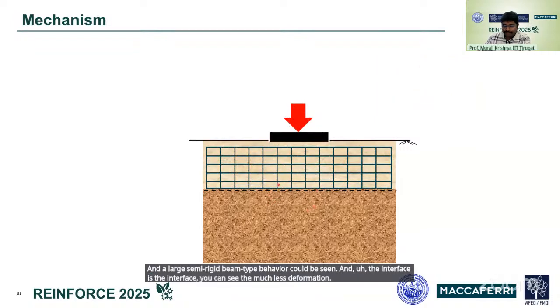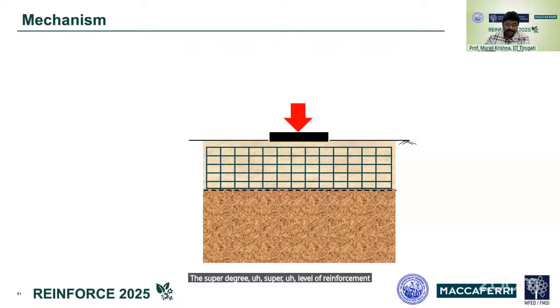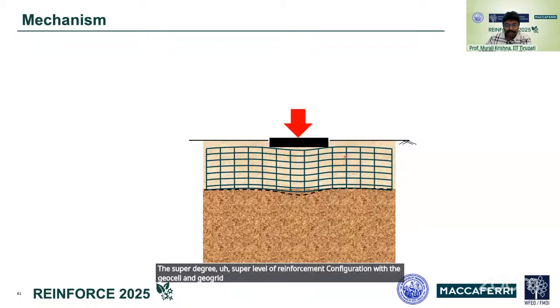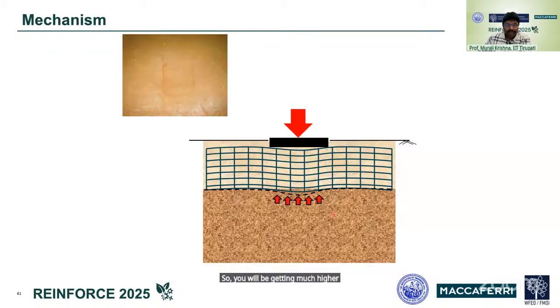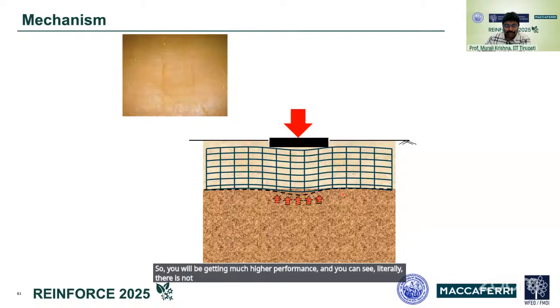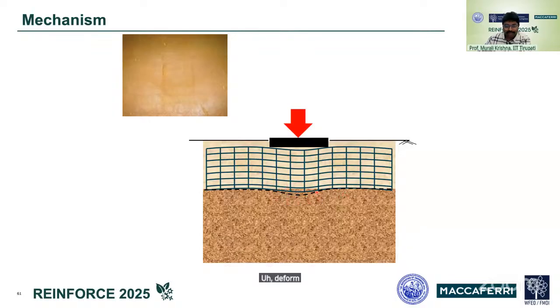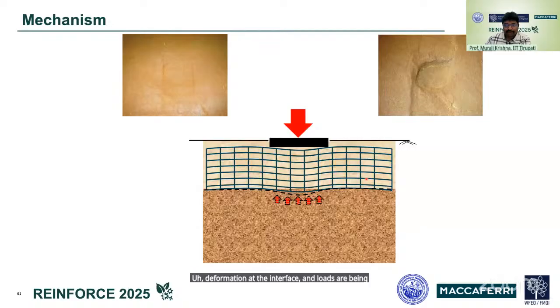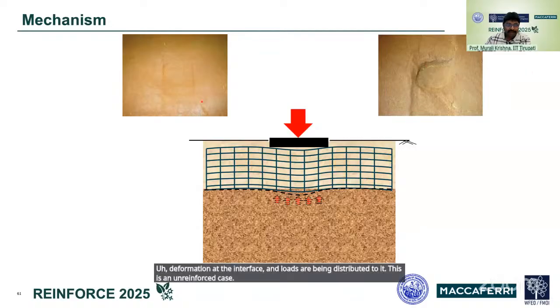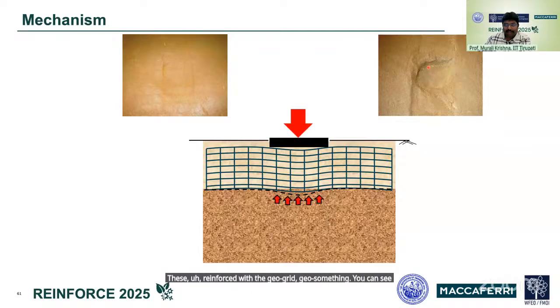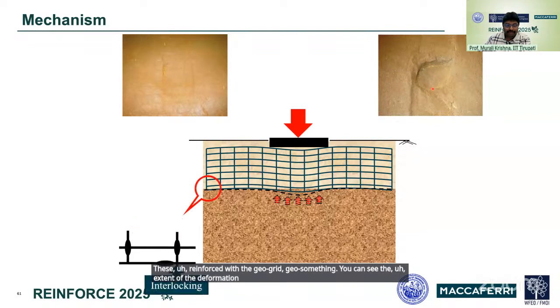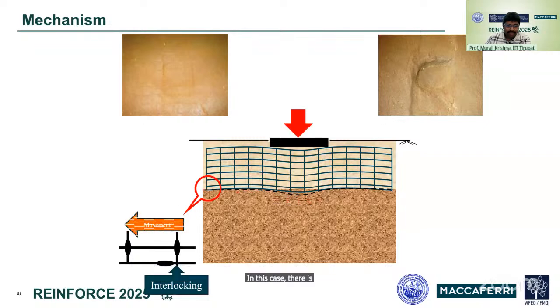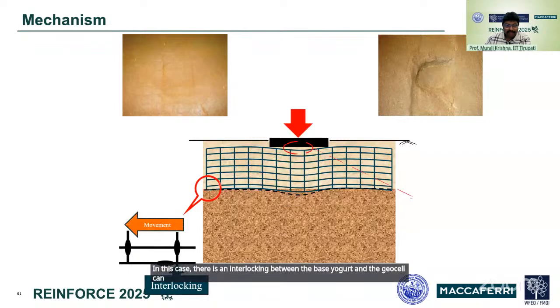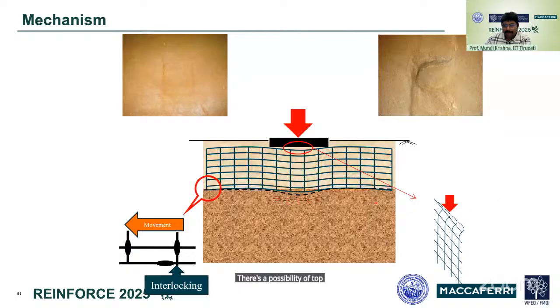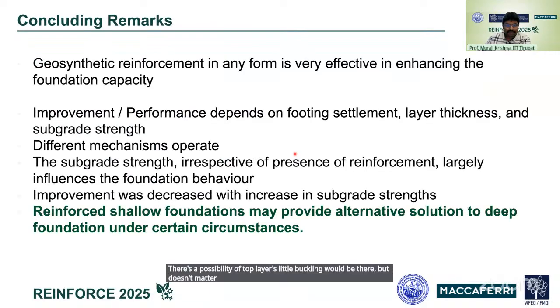With the super level of reinforcement configuration, the geocell and geogrid placed together, you will be getting much higher performance, and you can see literally there is not much deformation at the interface, and loads are being distributed too wide. This is an unreinforced case. This is reinforced with the geogrid geocell. You can see the extent of the deformation at the interface and so on. In this case, there is an interlocking between the base geogrid and geocell, which will be providing much support. There is a possibility of the top layers buckling a little, but it doesn't matter. Your performance will be good.